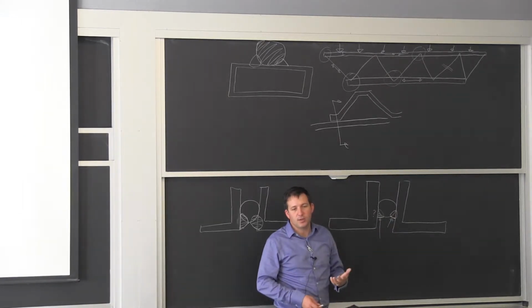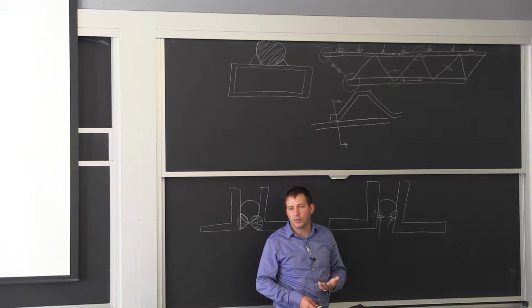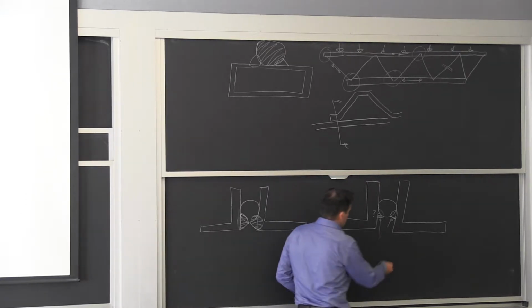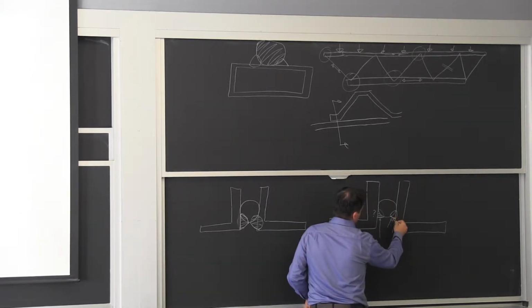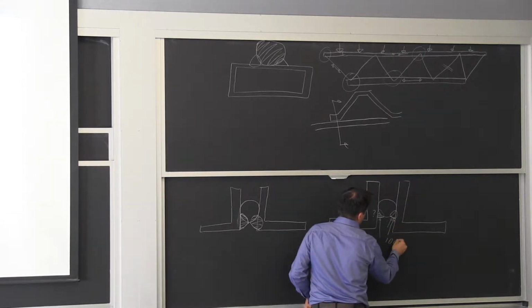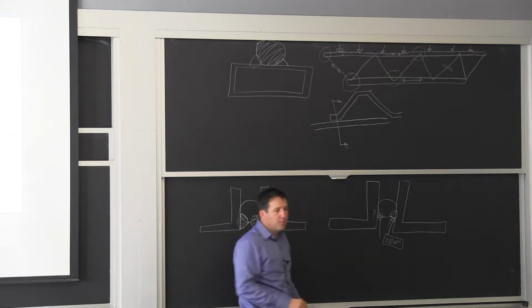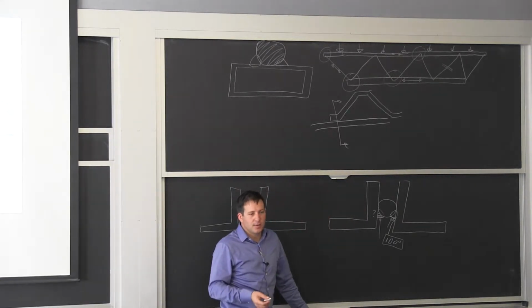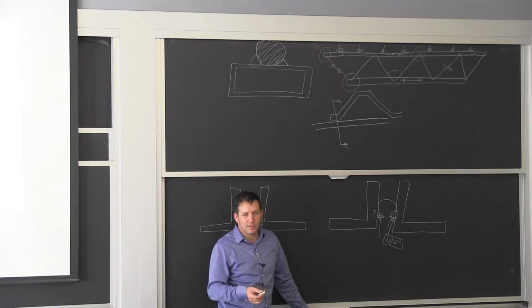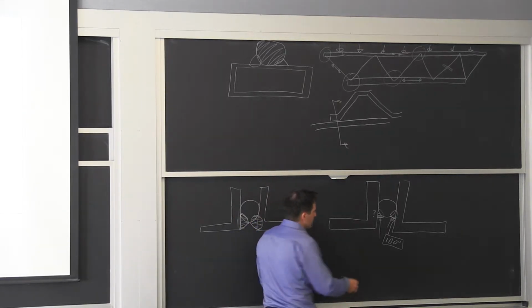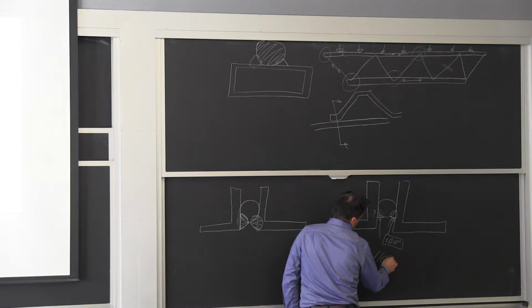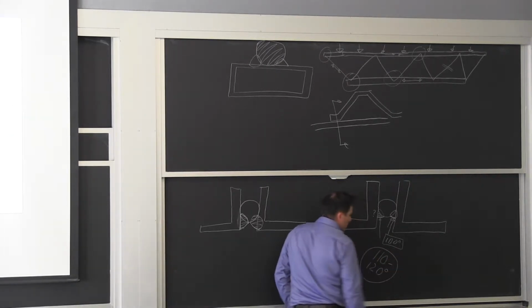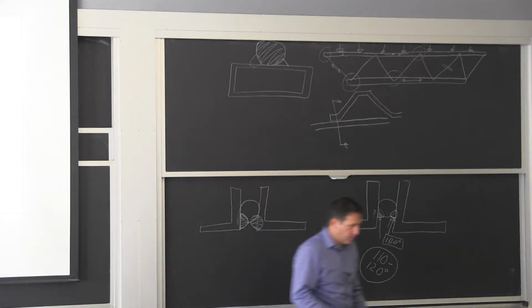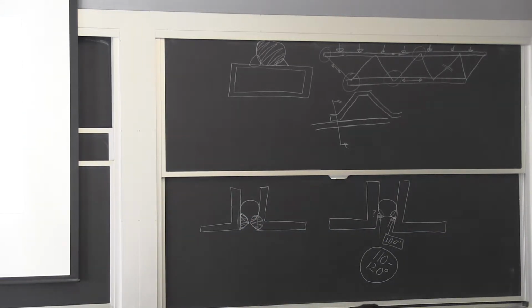And when you reach 90 degrees, you just can't guarantee you have fusion. So over here, we have, say, 100 degrees at this included angle. And if 90 degrees is the very, very bare minimum in the categories of the ISO standard, 100 is just a little better. And when you're looking at 110 degrees to 120 degrees, that's really what you would like to make sure that you have the fusion. Now let's pass some of this around.